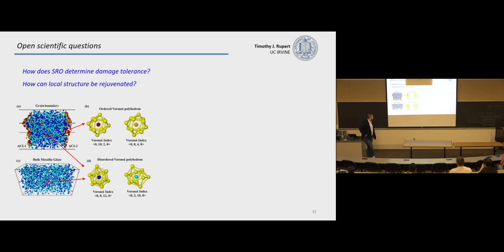Okay, so with that, I want to leave you with some open scientific questions we have. One thing we're digging into now that's really exciting is these amorphous regions at the grain boundary are quite interesting because they actually interact with the crystalline material next to it. So this is a model of a bulk metallic glass. It's primarily composed of these disordered types of packing structures. The interior of an amorphous grain boundary looks like that, but this region at the edge where it starts to hit the crystal looks very different and has a much higher density of these ordered packing motifs.